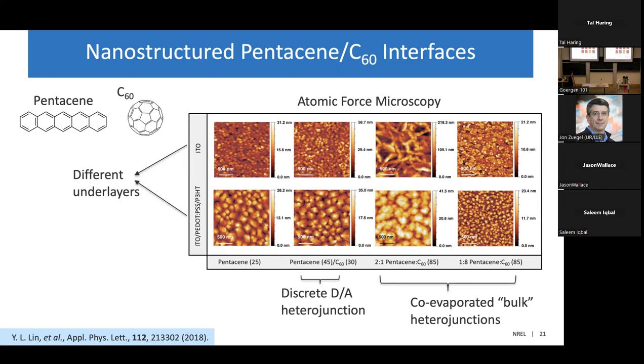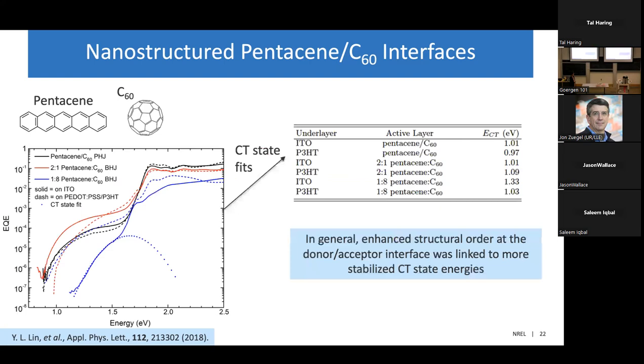And we can go through the same exercise again, where we build the solar cells and characterize the charge transfer state energies of these interfaces. And in general, what we see is that when there's enhanced structural order at this donor-acceptor interface, this is linked to a lower charge transfer state energy that's more likely to extract the triplets that are being generated by the fission material.